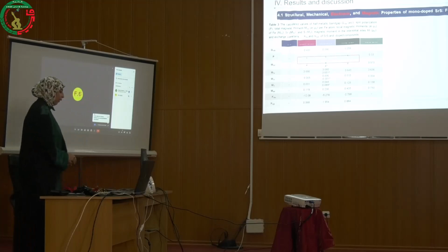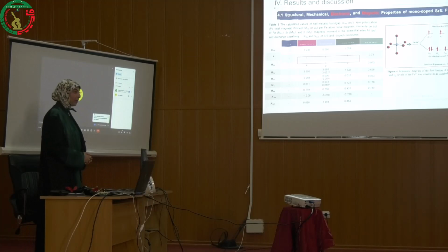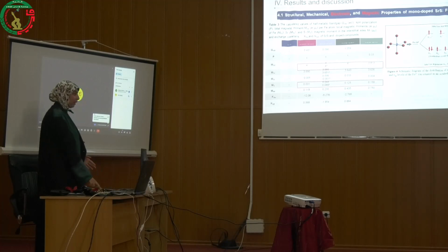The magnetic properties are calculated in terms of magnetic moment and exchange constants. The magnetic moments are found to be an integer value of 4 Bohr magnetons, which conforms well with the spin splitting energy and Hund's rule. The most contribution to this value comes from iron and interstitial sites, whereas due to p-d hybridization, local magnetic moments are created on the non-magnetic sites of strontium and sulfur.